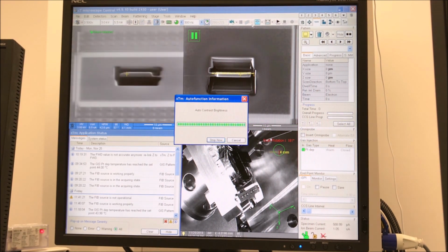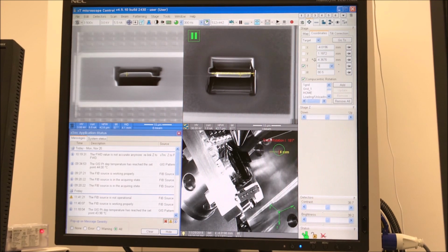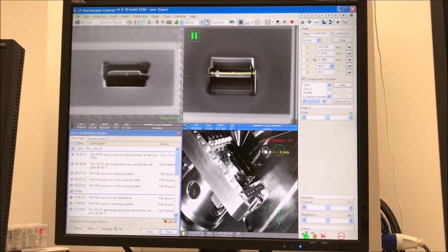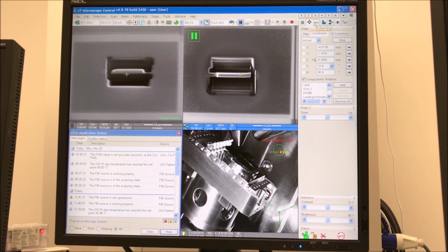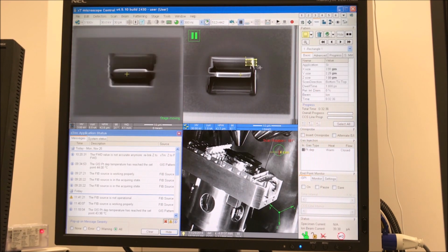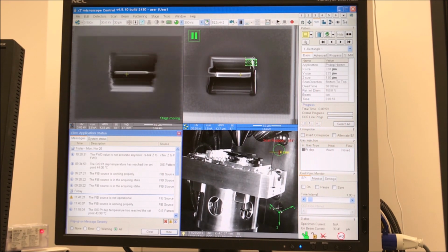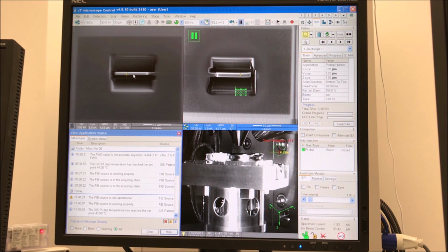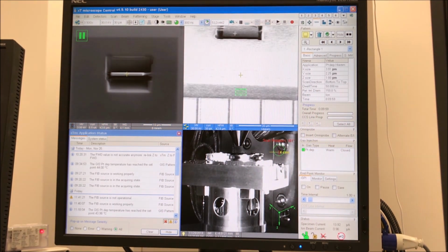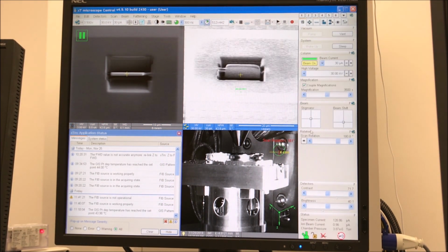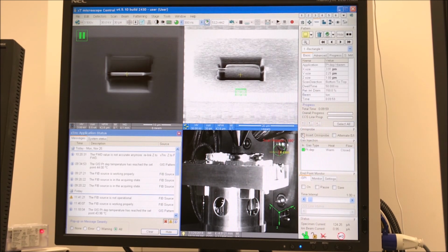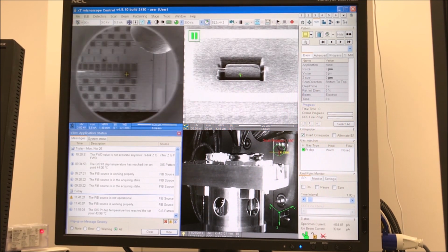All right, so the cleaning cut is done, and so now we can do the lift out. The first thing I did was turn off averaging for the E-beam, and then I tilted back to 0 degrees for the stage. I dropped my ion beam current to 30 picoamps. You can see now my ion beam image again needs to be shifted back, and again I'm making a fine tweak to the scan rotation just to square the lamella up in the ion beam image.